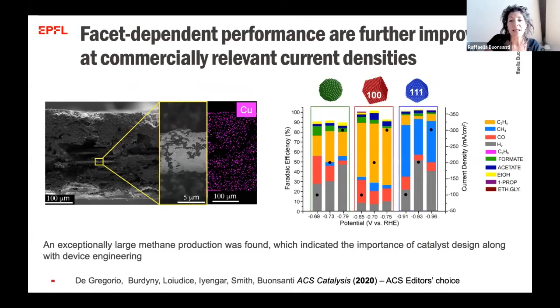One thing I would like to highlight is also that while these first studies were performed in still ideal conditions, we were also able to translate this performance to high current density. Because these nanocrystals come as inks, we can also integrate them in what is referred to as a carbon felt. So this is a gas diffusion electrode, and we can feed CO2 as a gas. And the currents that I'm reporting here this time are commercially relevant current densities.